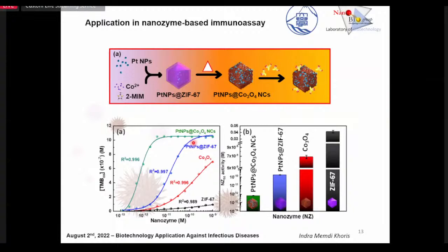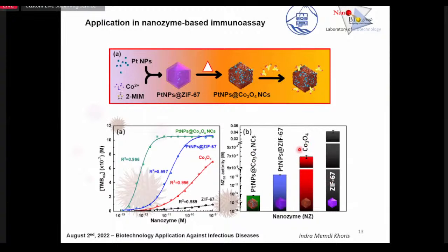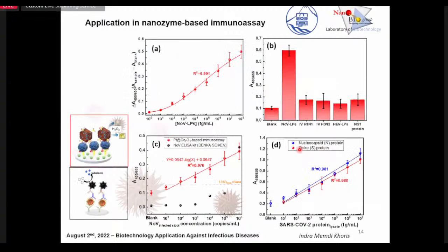kinetic parameter of non-enzymatic reactions, together with some sigmoid curve analysis, which is usually used in drugs, which we call IC50. Here we call it NZ50, nanoenzyme half reactions. Then we can indicate that the platinum nanoparticles within the nanocage are much stronger, or I mean, this requires a small amount to exhibit a high activity compared to the normal nanocage without nanoenzymes, showing the heterostructure actually improving, showing the concept of nanocage and nanoenzyme together.